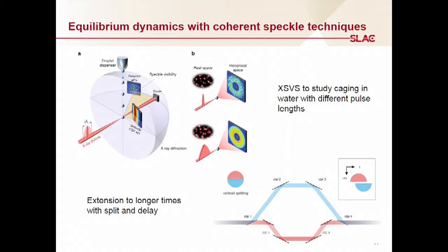And so what you have to do there is use a different technique, where you look at how the speckle contrast decreases with either two pulses, which are nanoseconds apart, or with a single pulse that is a certain amount of time long. So let's say you have dynamics on the time scale of 100 femtoseconds. That means if you use a 1 or 10 femtosecond pulse, your speckle contrast should be sharper than if you used a 100 femtosecond pulse, because your system is evolving within those 100 femtoseconds, and so you would have this blurring out in the speckle contrast. So this is what they did here.